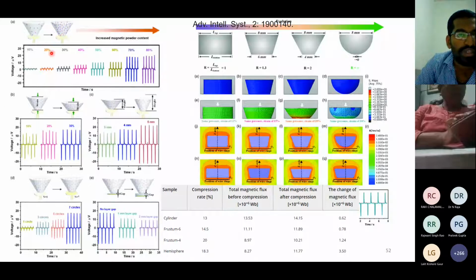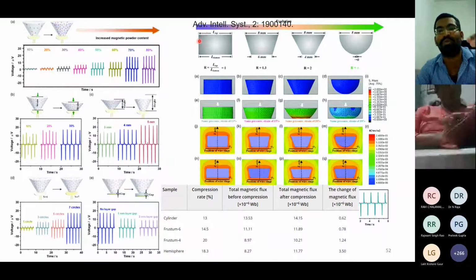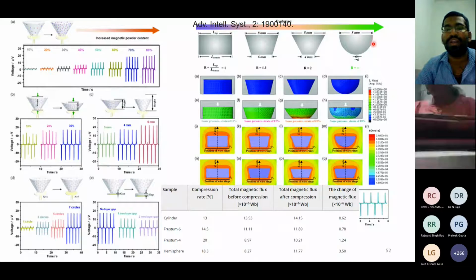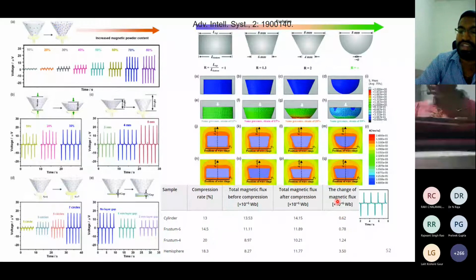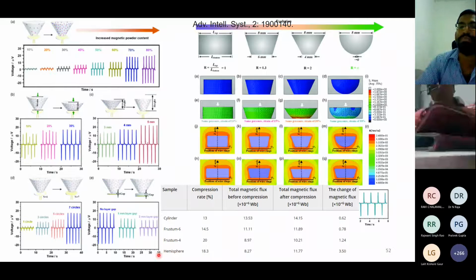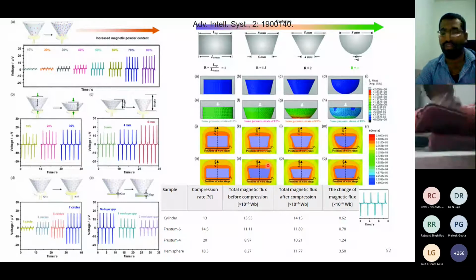So here you can see upon increasing the magnetic powder content, what happens: your voltage generation is getting higher. And if you can tune this kind of structure, here you can see this is flat, both sides on top and bottom are the same. But if you tune this to 6, 4 and 0 like a hemisphere, then your performance is going to get enhanced. So this kind of magnetic flux, the change in magnetic flux, is important. If you can optimize your structure like this, the change in magnetic flux can be achieved very well in the case of a hemisphere. So with the help of fine tuning your microstructures, we are able to get very good results in terms of electricity generation.